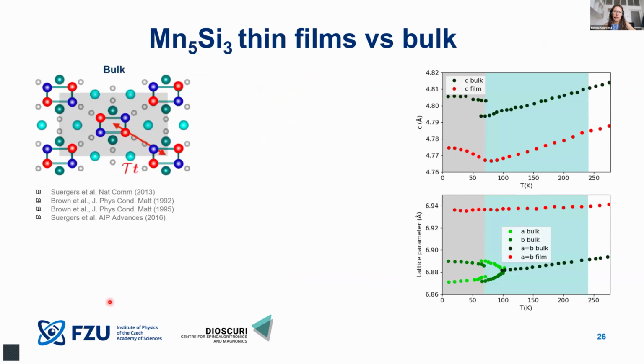And I will now look at another material, manganese 5 silicon 3, where the situation is a little bit more complicated, because bulk crystals have several phases, and one of them is this collinear phase with the underlying tetragonal crystal structure, which is a perfect antiferromagnet, exactly in the definition which I gave before. So it has the T tau symmetry. We do not expect any anomalous Hall effect, and people do not measure any anomalous Hall effect. So this is the bulk.